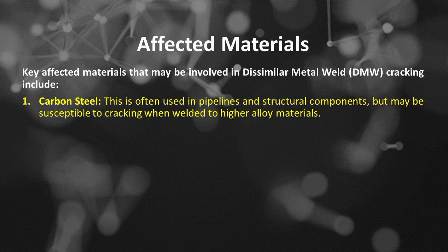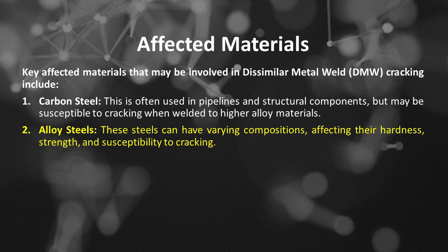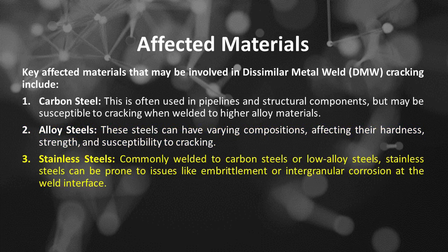Key affected materials that may be involved in dissimilar metal weld, or DMW, cracking include: Number 1 is carbon steel. This is often used in pipelines and structural components, but may be susceptible to cracking when welded to higher alloy materials. Number 2 is alloy steels. These steels can have varying compositions, affecting their hardness, strength, and susceptibility to cracking. Number 3 is stainless steels. Commonly welded to carbon steels or low-alloy steels, stainless steels can be prone to issues like embrittlement or intergranular corrosion at the weld interface.